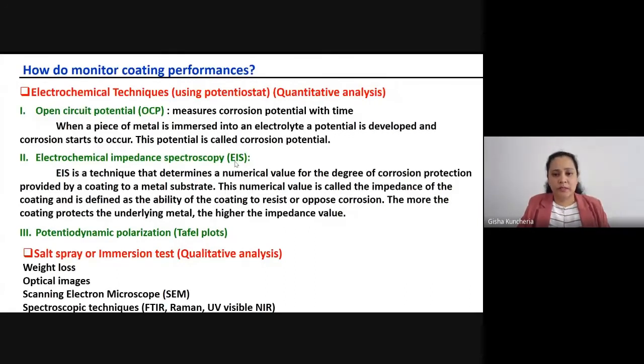Electrochemical impedance spectroscopy is a little bit complicated technique, but this is the best technique to analyze the performance of a coating. Then potentiodynamic polarization, Tafel plots. Tafel plots show corrosion current versus potential. Corrosion current, corrosion potential and corrosion rate, all these you can get from the Tafel plots. Qualitative analysis includes weight loss of the substrate, optical or microscopic images, or spectroscopic techniques, which you can also use to identify the structure of the corrosion products.